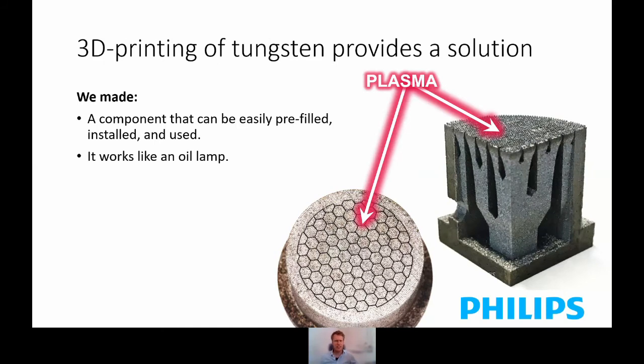We came up with the following. Let's do some 3D printing. So Philips has developed for X-ray optics the capability to print tungsten. And you can do something fantastic with this. Namely, we designed a component that works a bit like an oil lamp. So there's a reservoir, there's capillary flow to the plasma facing surface, and then that plasma facing surface is supplied completely automatically, passively, with liquid metal. And this works very practically.